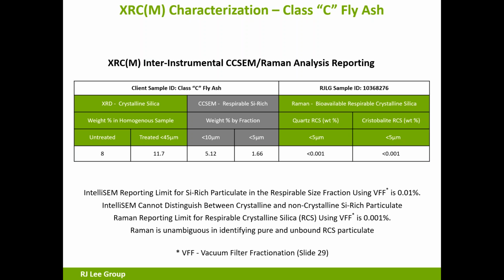The IntelliSem reporting limit for silica rich is 0.01%. The Raman reporting for crystalline silica is 0.001. When we hit none detect, we consider it to be non-crystalline silica containing for purposes of Prop 65, either one of those limits. We then advise that it does not need labeling under Prop 65. VFF, as I'm going to describe in a minute, is vacuum filter fractionation. This was not done with that method.